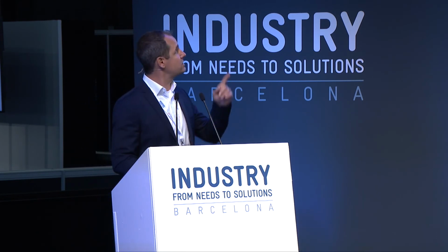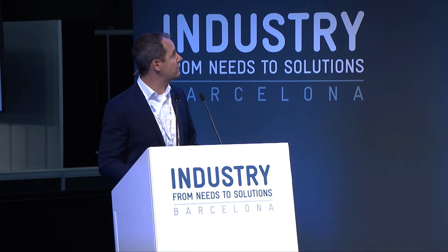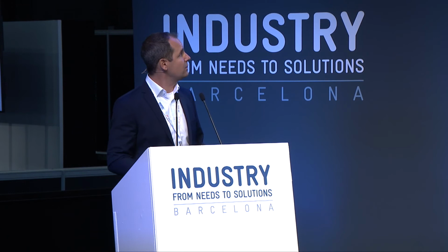And you see already here, a big part of this production is always ensuring the quality. This is why you see on the build plate here these tensile bars. So we always have to produce tensile bars, density cubes, when we do structural parts, which are ending up on the race car. Then once we have the parts produced, we do validation.